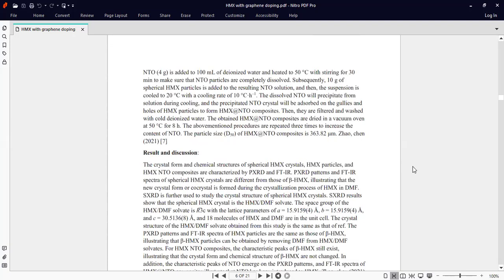NTO 4 gram is added to 100 ml of deionized water and heated at 50 degrees Celsius with stirring for 30 minutes to make sure that NTO particles are completely dissolved. Subsequently, 10 gram of spherical HMX particle is added to the resulting NTO solution and then the suspension is cooled to 20 degrees Celsius with a cooling rate of 10 degrees Celsius per hour.